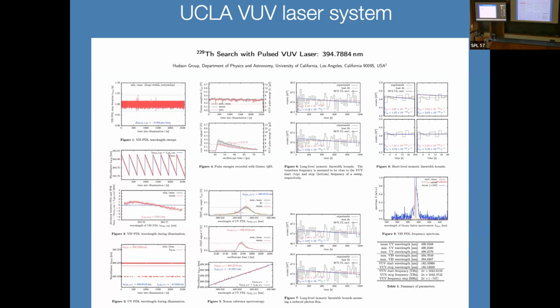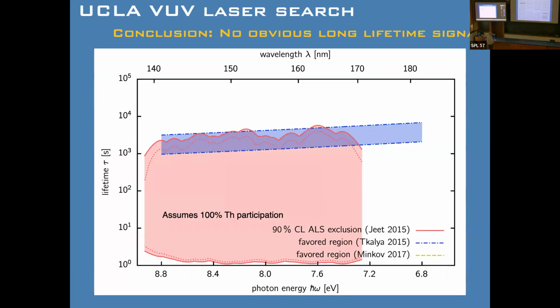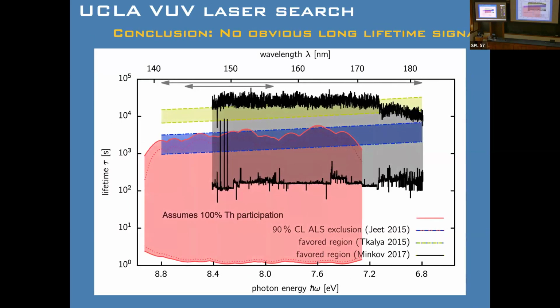This is the number of collected photons versus time, and you hope to see a nice big decaying exponential if you see the transition. And we saw nothing. We could set an exclusion that looked something like this. Now, I say a qualifier here: I say there was no obvious long lifetime signal. We expected that this transition would have a 500 to 1,000 second lifetime. We didn't see anything like that.